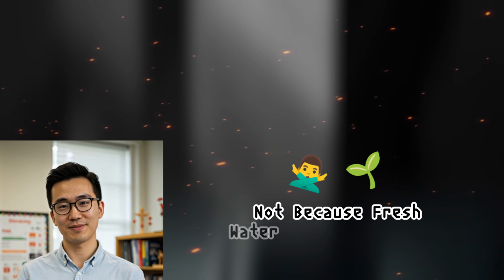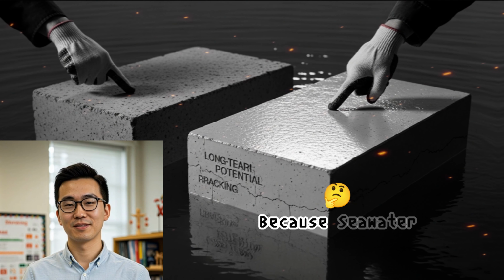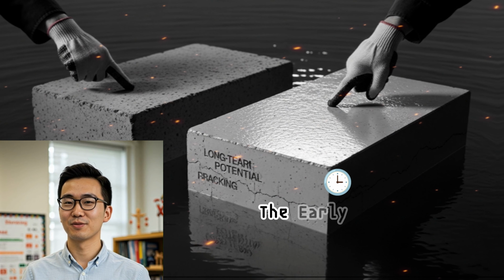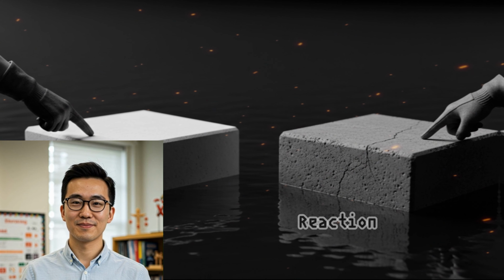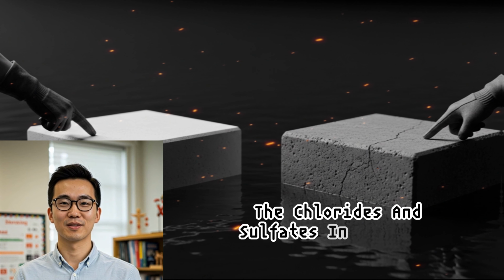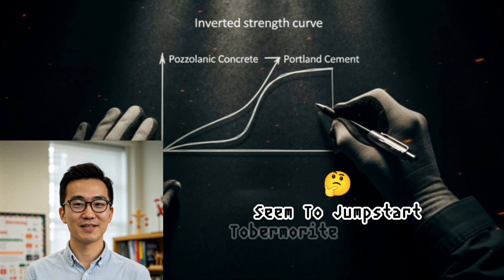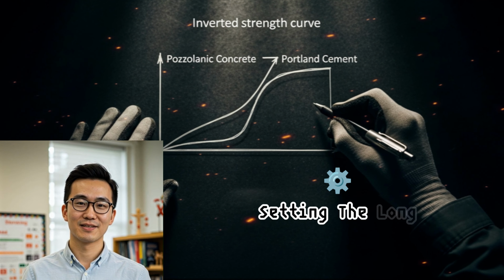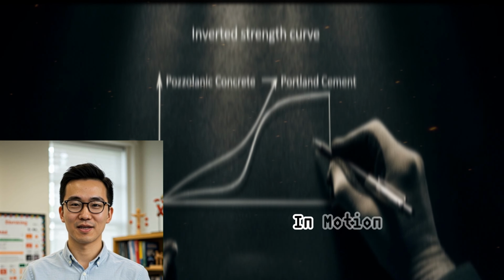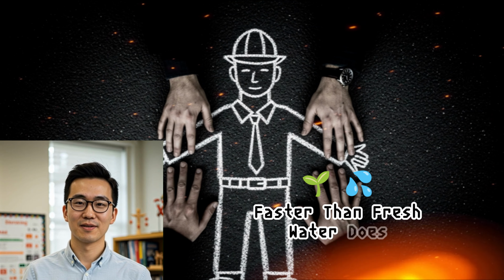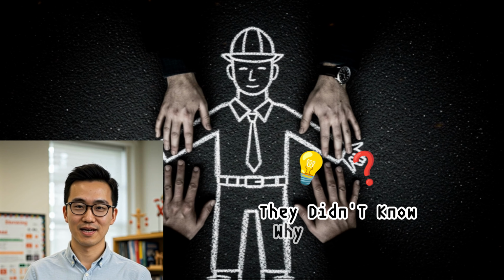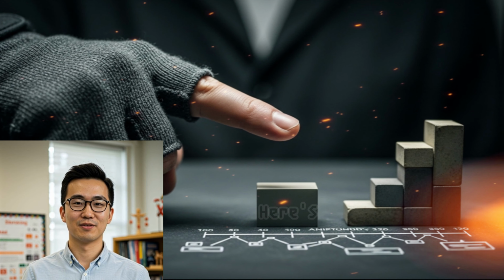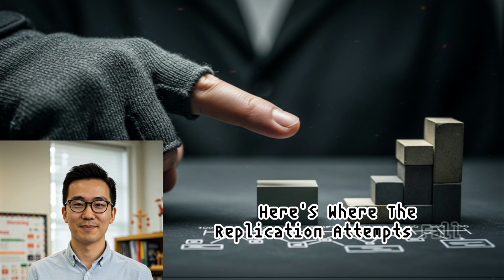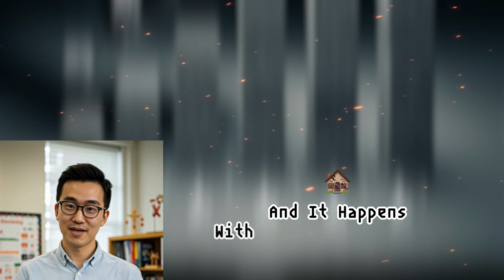Not because fresh water wasn't available, because seawater appears to accelerate the early stages of the pozzolanic reaction. The chlorides and sulfates in seawater seem to jumpstart tobermorite nucleation, setting the long-term strengthening process in motion faster than fresh water does. They didn't know why. They knew it worked. Here's where the replication attempts fall apart. And it happens with experienced builders, not just beginners.